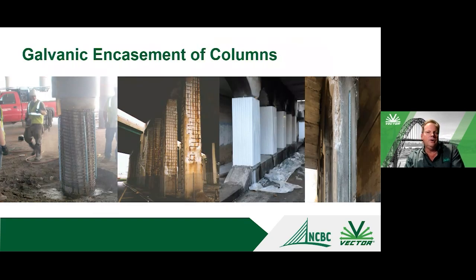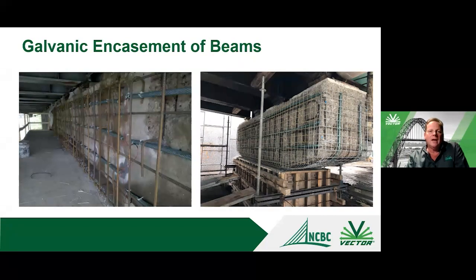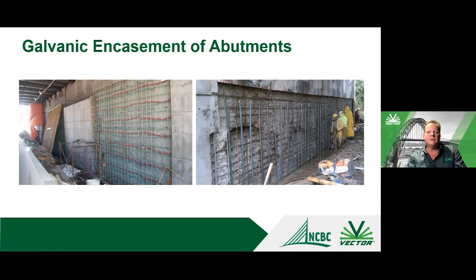We also talk about, when you get into more severely deteriorated structures, looking at galvanic encasements, and this will be the topic of pretty much a whole series in a few months. But effectively, the idea here is you're using galvanic anodes on more severely deteriorated structures, and you're reinforcing it with a new layer of steel. The galvanic anodes are placed into that overbuilt section, connected back into the existing reinforcing steel to provide corrosion protection, and then you have concrete placed. And this is commonly used even for abutments.